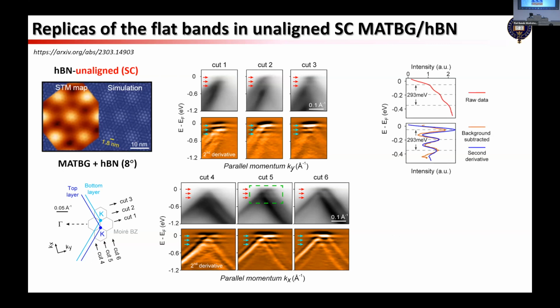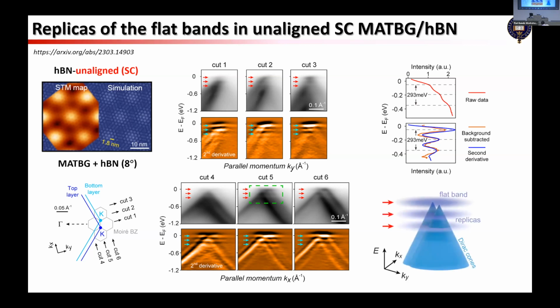If you still want to analyze it carefully, we can integrate this intensity over the momentum space, and then do this density plot. You can clearly see there are three kinks here, and by using the technique we learned from the transport community, for example quantum oscillation, we subtract this smooth background, which is effectively similar to the second derivative, and you can see there are three oscillations here, and the amplitude just decreases. And this is a not so good cartoon to show that there's a flat band and there are replicas at a higher binding energy.